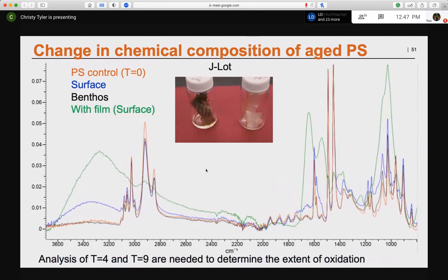Finally, looking at JLOT, where we saw a large difference in the film being formed at the surface versus the benthos, if we look at the plastic itself, so the blue versus black and the orange, there are some subtle differences, but there isn't a large amount of difference. What I also have on here is the biofilm itself. That's the spectra in green. What's different about the film from JLOT compared to the others is that this is a very robust film. There is a very strong adsorption of this film on the JLOT sample. To remove the film, I had to actually use isopropyl alcohol and really rub it off to be able to get the spectra of just the plastic itself.